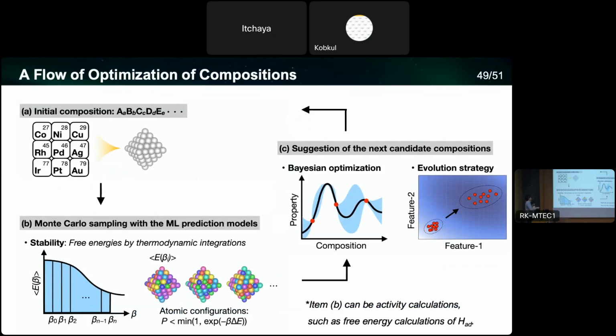the computational flow that we are doing is like this. First, we randomly set the compositions like this, as mentioned earlier, the combination of A, B, C, D, E, randomly from the 9 elements. And then we calculate, for example, in the case of stability, the free energy by using thermodynamic calculations. We choose this because we want to consider the configurational entropy precisely, not the ideal one.